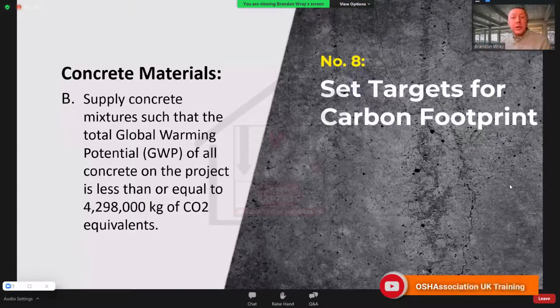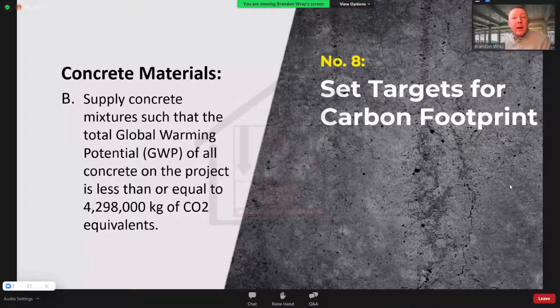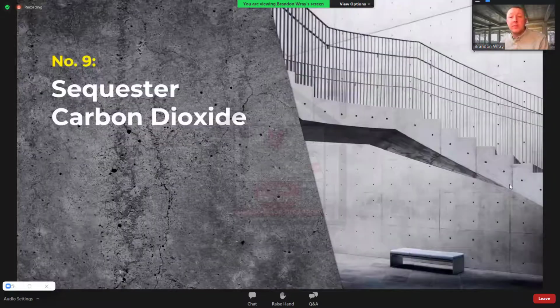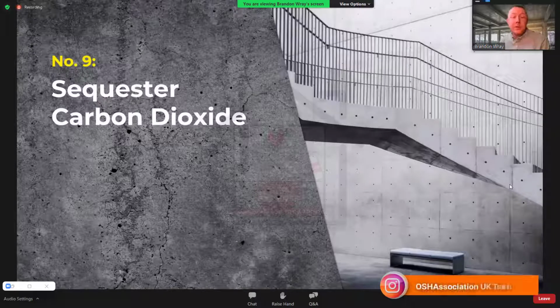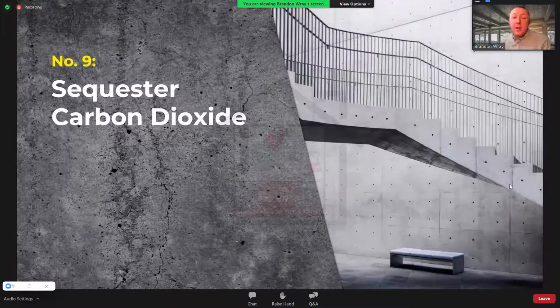Carbonation, a naturally occurring process, CO2 reacts with the surface of concrete. Carbonation is a slow process with many variables, and the rate does decrease over time. This is because carbonation itself does decrease permeability, and carbonation does occur from the surface inward, creating a tighter surface matrix and making it more difficult for CO2 to diffuse over time. While slow, though, the carbonation process does result in some uptake of CO2 emitted from cement manufacturing.